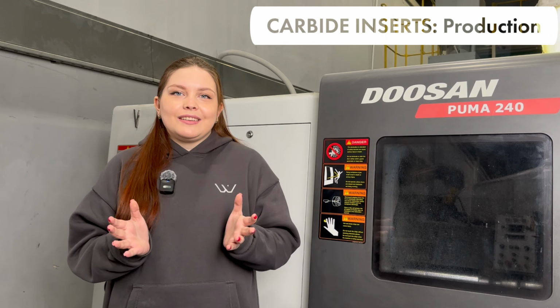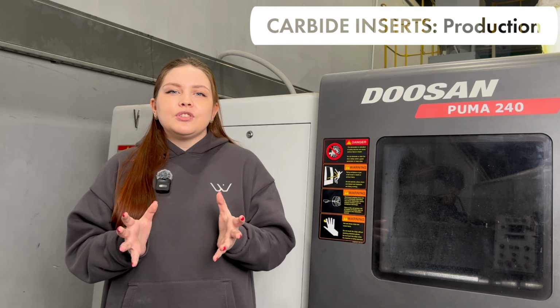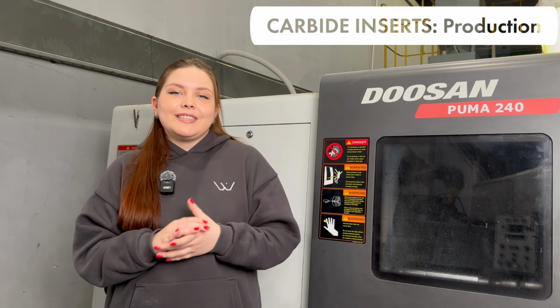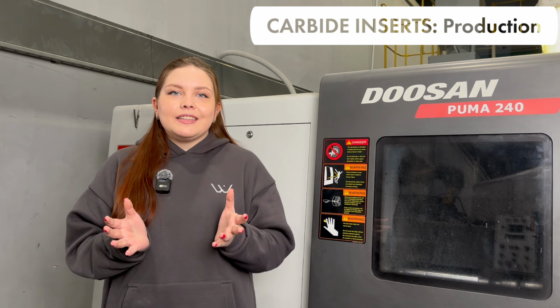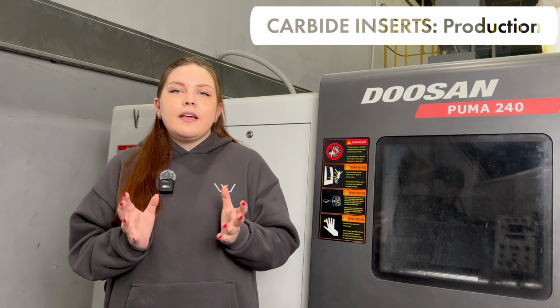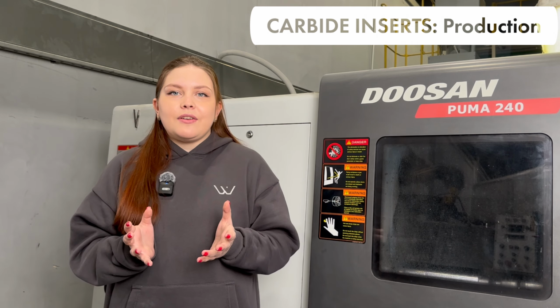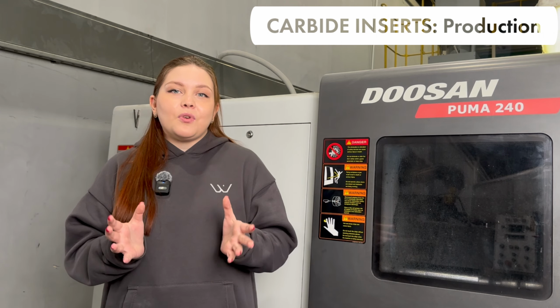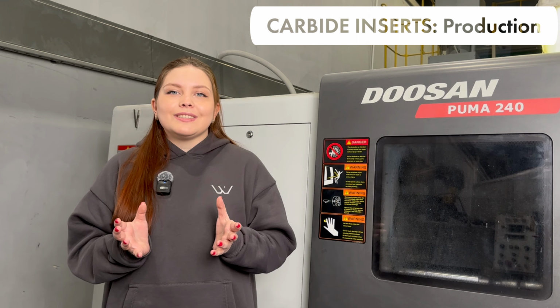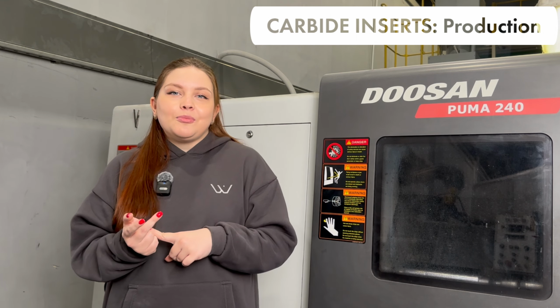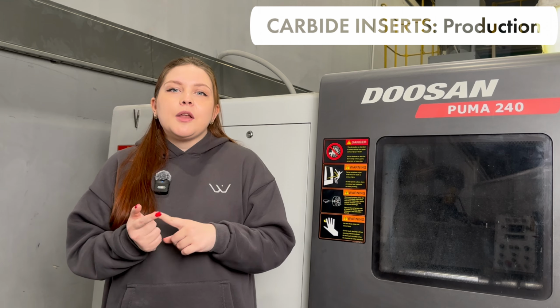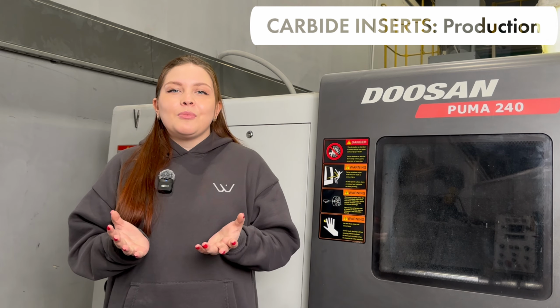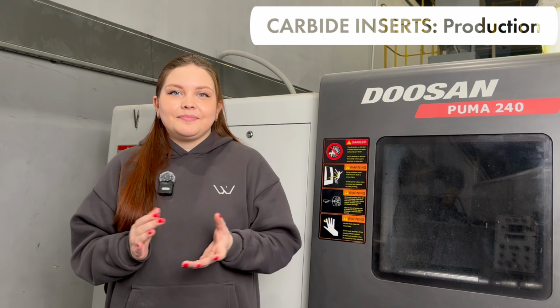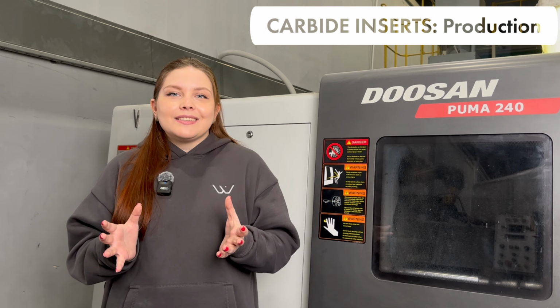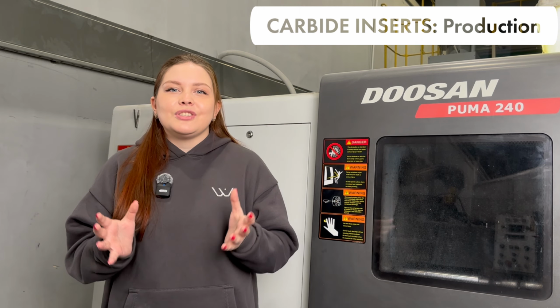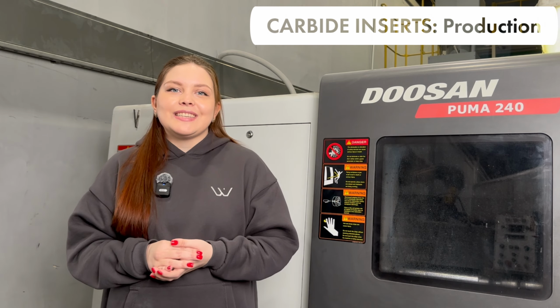Now precision grinding comes into play, where it's shaped with utmost accuracy to meet the strict quality standards. Then some carbide inserts get an extra layer of coating. These coatings enhance wear resistance and reduce friction, optimizing cutting performance. We usually use such coatings as titanium nitride, titanium carbonitride, aluminum oxide, and more advanced ones, for example, titanium aluminum silicon nitride coating.